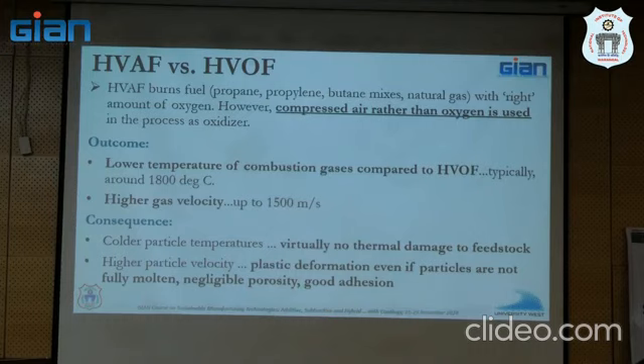So today, if we do an adhesion test, there is, by the way, an ASTM standard, C633-79. You coat a 1-inch button, right? And then glue it to another 1-inch button, right? And try and pull it apart in a UTM, right? And the force at which you pull it apart is the bond strength or adhesion strength of the coating, right? That's how it's done. So when we do HVAF, we always get failure in the glue. We never get, because there's no glue hard enough to kind of overcome that bond strength. So we have come up with new ways of testing, like brazing or something like that, to be able to do that test. Yeah, so it gives you excellent adhesion, almost no porosity and things like that.